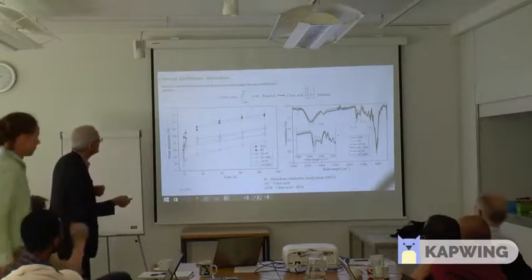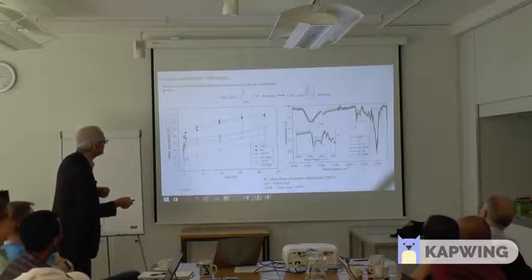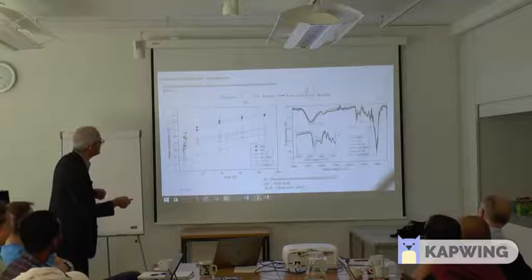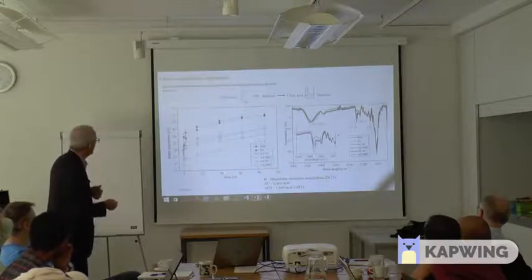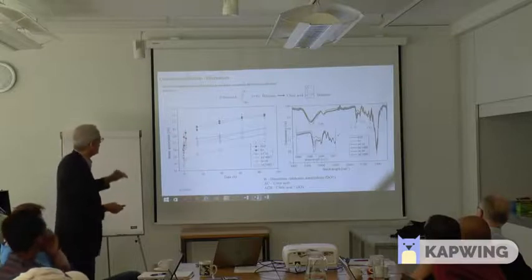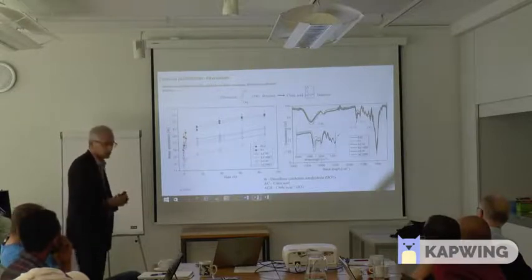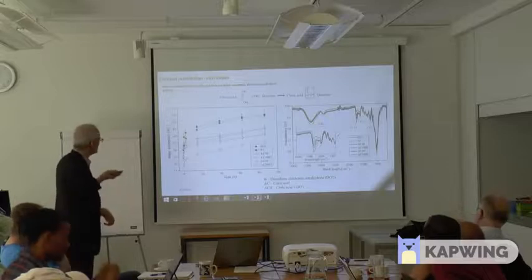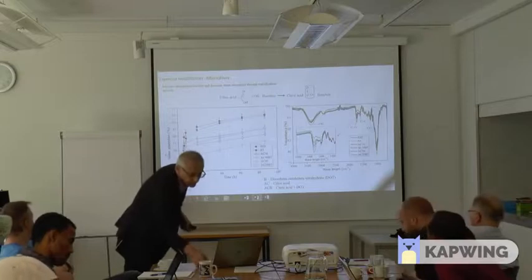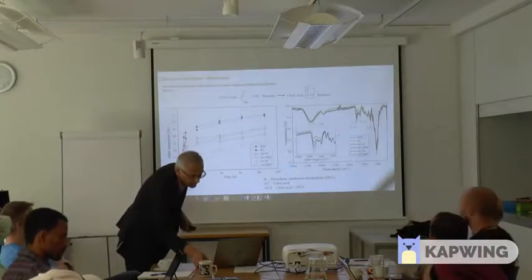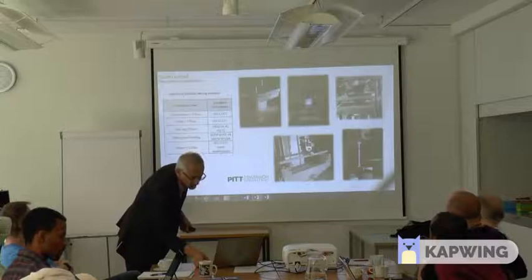And in here we can see the C double linkage with oxygen. That's the modification in the structure of the wood that can help us to explain why this is happening, how we are achieving this reduction of water absorption using, in this case, the citric acid. So this is part of that study as well.